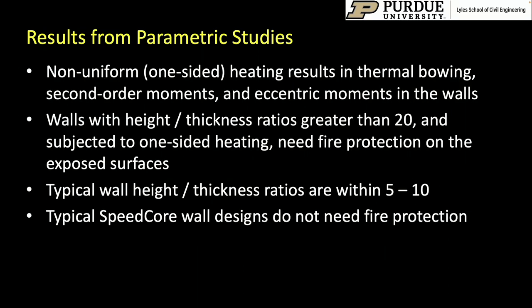We also conducted studies on non-uniform or one-sided heating, which we found results in thermal bowing, some second-order moments in the walls, and some eccentric moments as well. Walls with height-to-thickness ratios greater than 20, what I mean is story height divided by wall thickness ratios greater than 20, and subjected to one-sided heating, need fire protection on the exposed surfaces. But this never happens because of the thicknesses that are generally used in construction. Typical wall story height to thickness ratios are within 5 to 10. So this is just providing a theoretical limit on how far you can go. And what we concluded was that the typical SpeedCore wall designs do not need any fire protection. They can be designed unprotected.